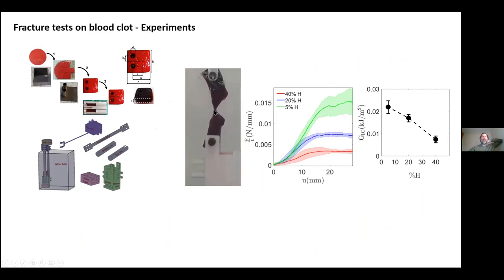And the reason again, we feel, is because the fiber network is becoming aligned in front of the crack tip and making it very hard. You see the crack becomes blunt, rounded before it will grow. So this is the indication of a material that really is resistant to fracture. And we found that the more fibrin in the clot, the more energy it takes to fracture the clot. In other words, the crack is more resistant to fracture if the fibrin content is high.